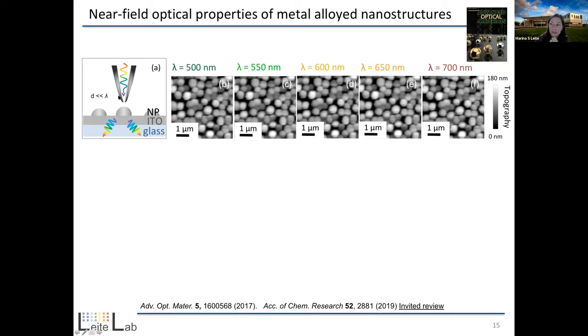So basically we do NSOM or SNOM, depending on who you talk to. In this case it's in transmission mode. This is a probe that has an aperture. We shine light through the probe and we can control the wavelength. Then, as we raster scan this probe on the surface of these metallic nanostructures, we also have an objective lens at the bottom, and we can capture all the light that is being transmitted.